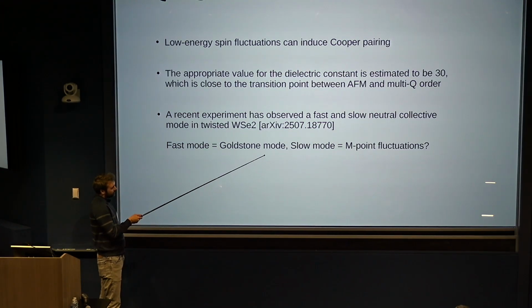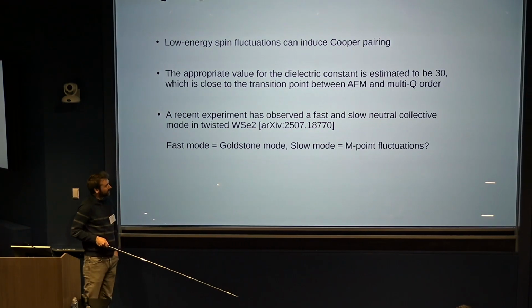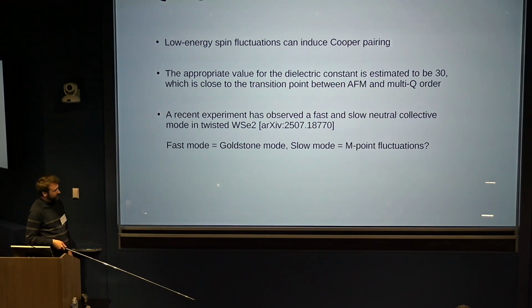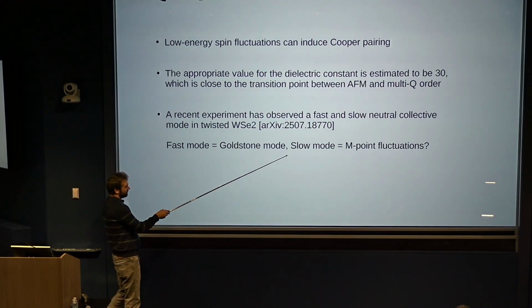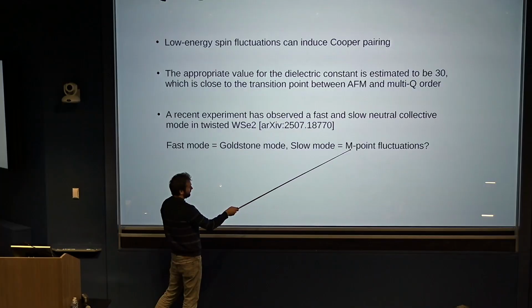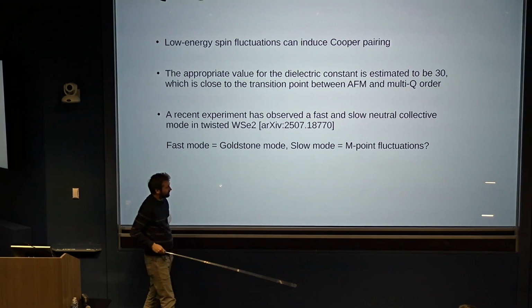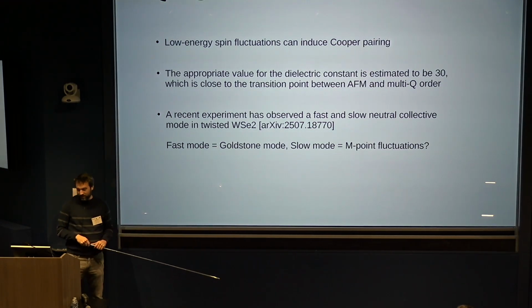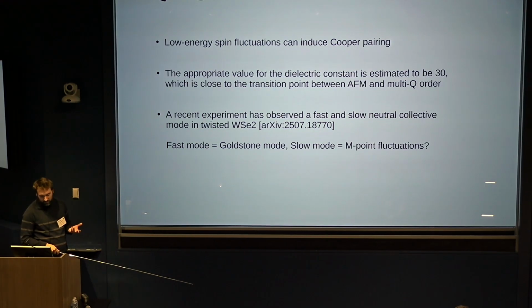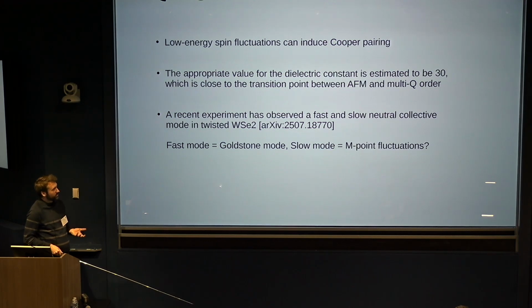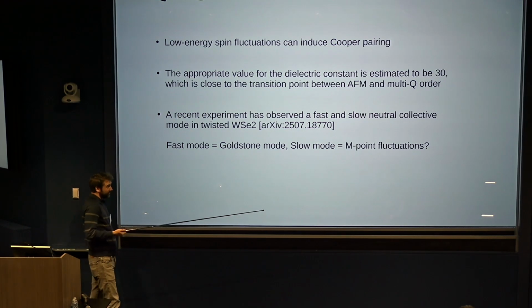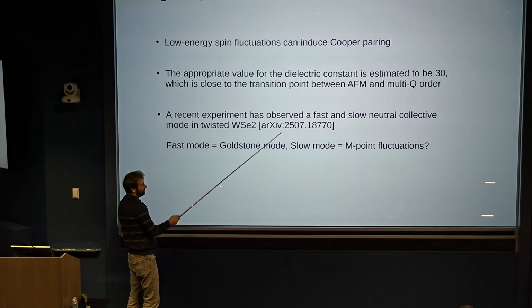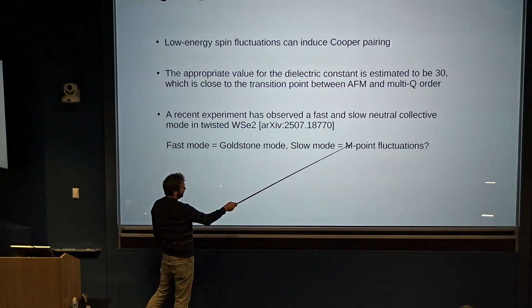But then they interpreted the slow mode as the amplitude mode. I think, actually, from these calculations, I would suggest that the slow mode they saw is actually these M-point fluctuations. And definitely in our calculations, the energy of these M-point fluctuations, the mass of these fluctuations, is at least an order of magnitude smaller than the mass of the amplitude mode. So I think what they saw in this experiment were these M-point fluctuations.